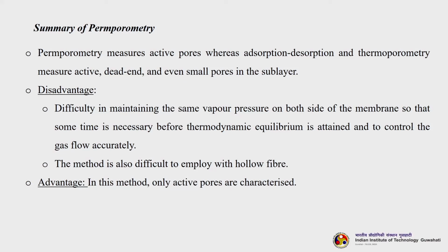In summary, we can say that it measures active pores only, that is the beauty of this particular technique, whereas adsorption-desorption and thermoporometry measure dead-end pores also. However, the disadvantage is the difficulty in maintaining the same vapor pressure on both sides of the membrane. You need to maintain the vapor pressure on both sides, because from one side we are flowing one non-condensable gas, nitrogen, and from the other side another one, oxygen. So, the method is difficult to employ with hollow fibers. Hollow fiber membrane characterization is very difficult, but the advantage is that only active pores are being characterized.